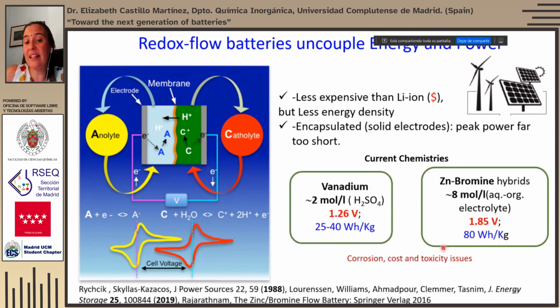And the current chemistries in redox flow batteries are vanadium, which is the most popular, in which you have the vanadium 2, vanadium 3 redox couple in the anolyte, and vanadium 4, vanadium 5 in the catholyte. Having the same chemical species is an advantage because you have a kind of symmetric battery where cross-contamination doesn't have such a big impact. Still, these aqueous solutions have quite a low pH as they are in concentrated sulfuric acid. The other chemistry that dominates redox flow batteries is that of zinc bromide, that reaches very large solubilities, up to 8 mol.